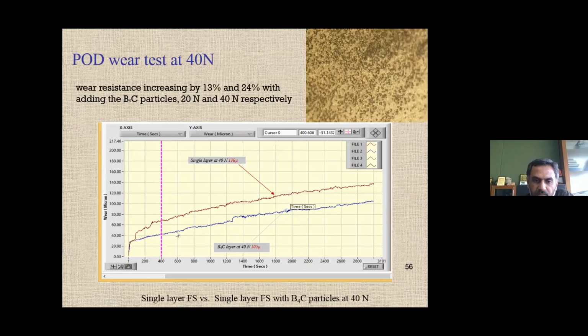You see the wear behavior of the normal single layer, which is close to around 138 micron, and here, which is close to around 105 micron. So there is a drastic reduction in the wear in terms of micron, right? So wear resistance increases by 13 and 24% with adding B4C particles, at 20 Newton and 40 Newton respectively.